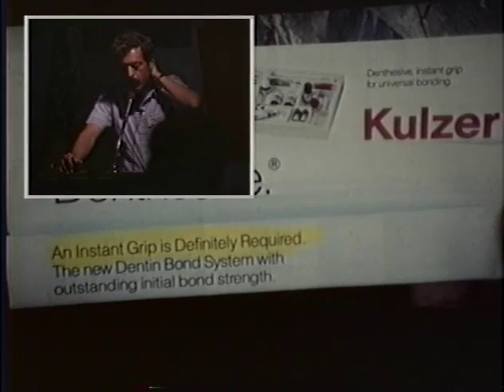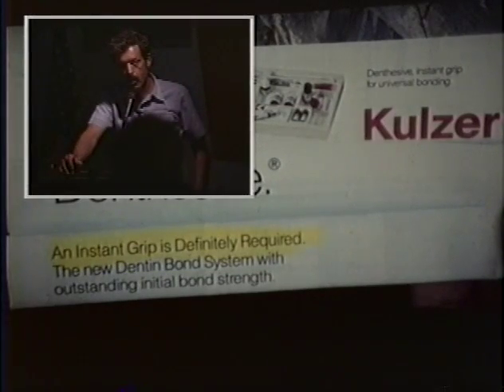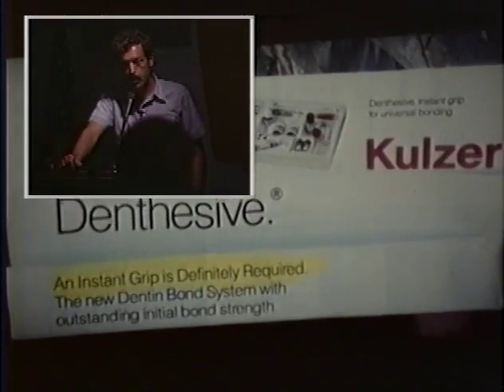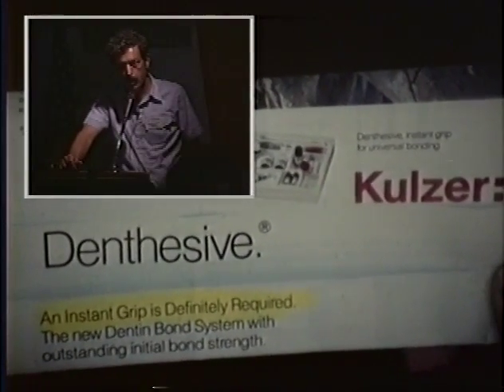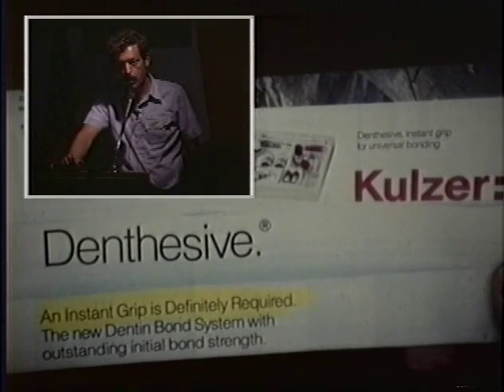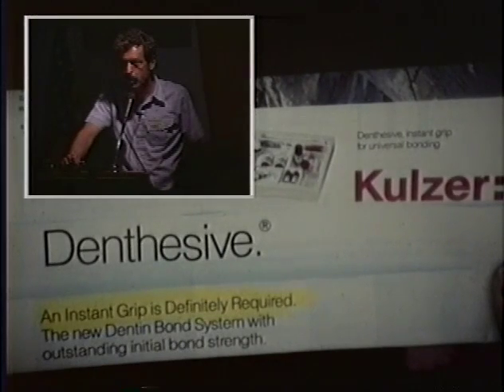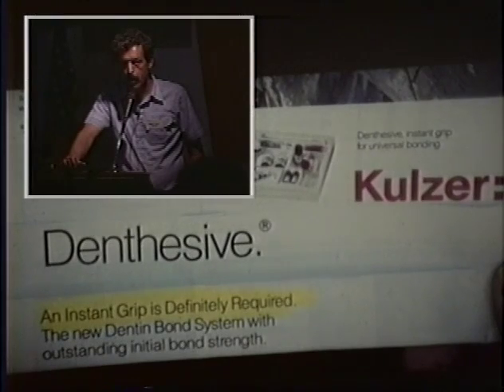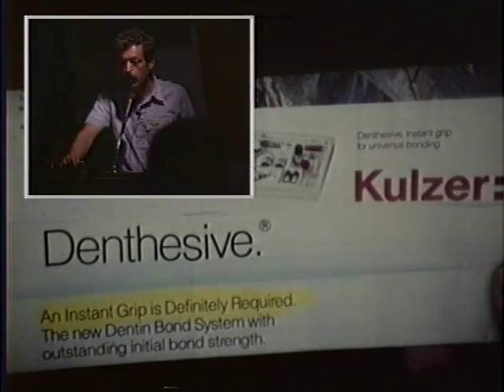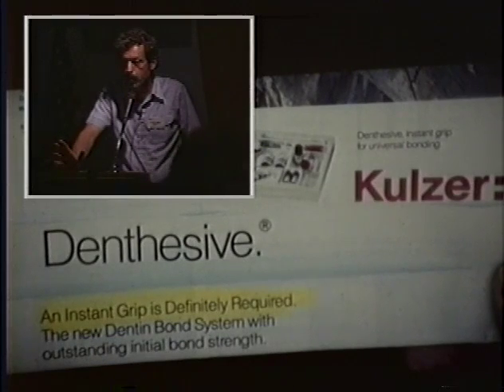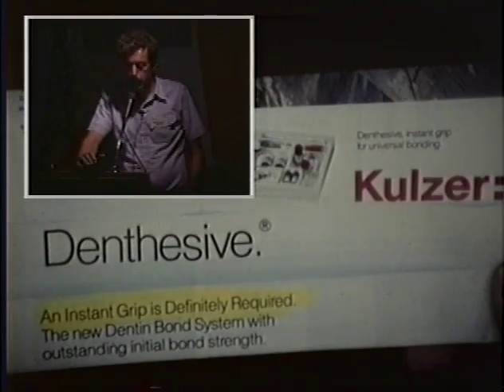Now, if any of you are using a bonding system where you cure the enamel bond at the same time as the composite, you've got big problems, because you can't possibly cure the bonding agent through the composite before the composite begins to shrink. That's physically impossible. And one set of directions that advocated just that was Gluma. Gluma number 4, you put that on and you cured through the composite, and the Gluma wasn't polymerized yet. All right, so anyway, that's a big problem.